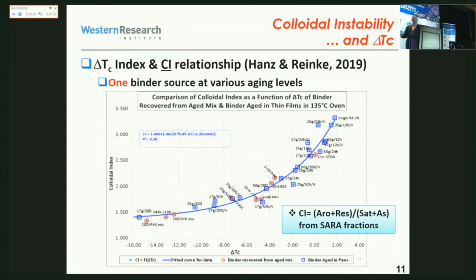We are not the only one looking at this. Hanz and Reinke, I think, were in the room. They did a study, and they used one binder source, and they aged it at different levels, and they measured delta TC on the x-axis, and they plotted the colloidal stability index, which is coming from the composition of the asphalt, and that's the ratio of aromatics plus resin divided by saturates and asphaltenes. Sorry for those who are not chemists, but chemistry is important. And they found a very nice relationship. So okay, colloidal stability or instability is the thing to look at. But remember, only one binder source.